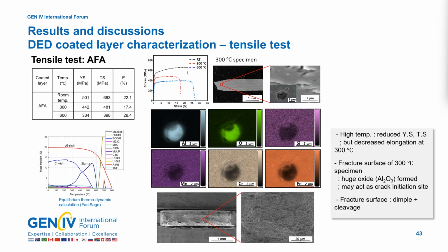To identify the cause of the reduced elongation, the fracture surface of the 300°C specimen was examined. The fracture surface showed a mixture of dimples and cleavage, and large aluminum oxides were observed in some regions. These aluminum-rich phases were calculated to have higher mass fraction at 300°C compared to 600°C. It is believed that these oxides act as crack initiation sites, leading to the reduction in elongation.